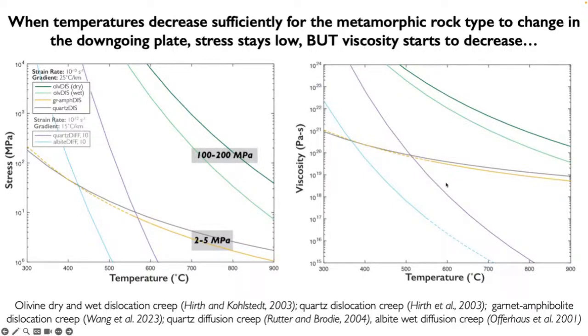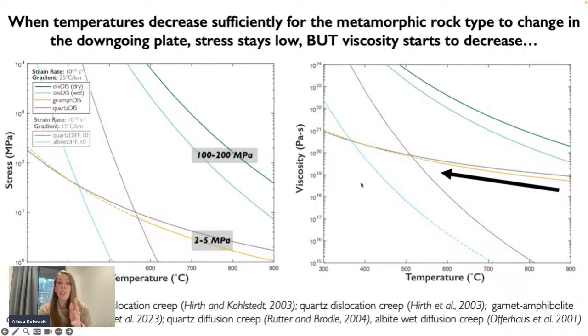These epidote amphibolites start to be created along the interface, and they have a very different rheology, a very different viscosity. What that actually shows is that through time, as we cool the interface down, by changing the metamorphic rock type and the deformation mechanism, this leads to an actual plummet in the viscosity of the interface. This purely reflects cooling of the plate boundary, changes in stable metamorphic rock types, which feed into changes in deformation mechanism and microstructure. All of this leads to this plummeting of the viscosity of the interface.